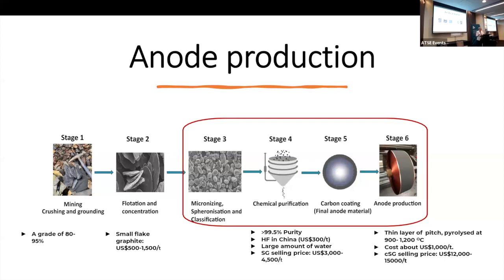Now, I would argue the most important thing in a battery is the carbon coating that goes on the graphite anode. It stabilizes the battery. It stops the anode from falling apart. This is a nano layer of carbon coating that's put on the anode material. People like EcoGraf and many other companies are looking at alumina coatings. This stabilizes what they call the solid electrolyte interface. So you get really good charging and discharging out of the battery, and it doesn't fall apart.